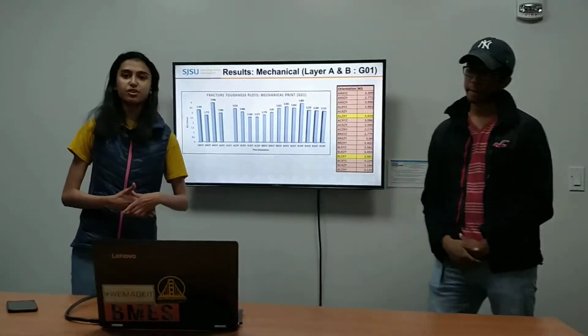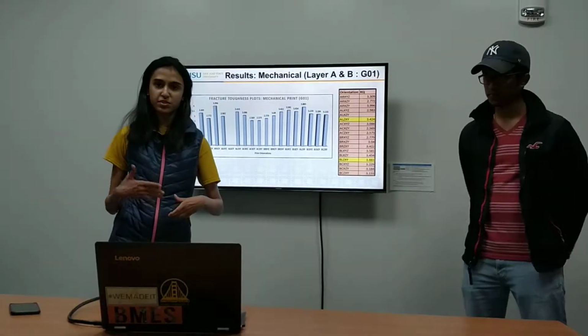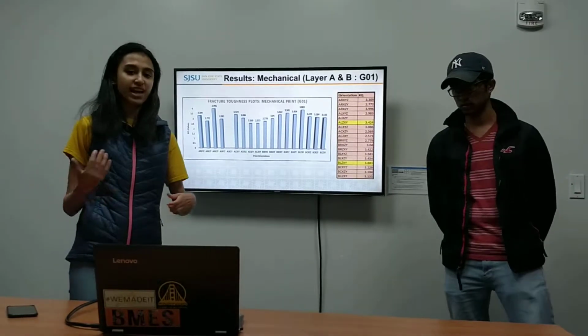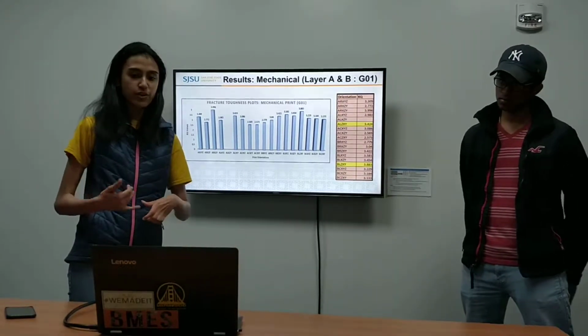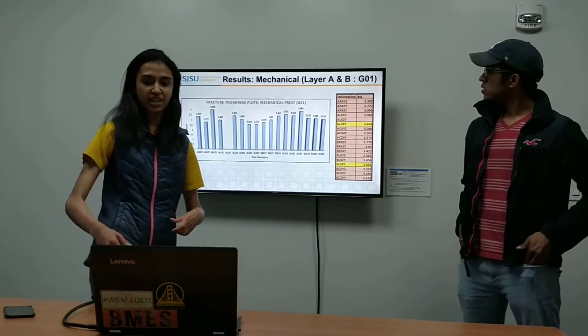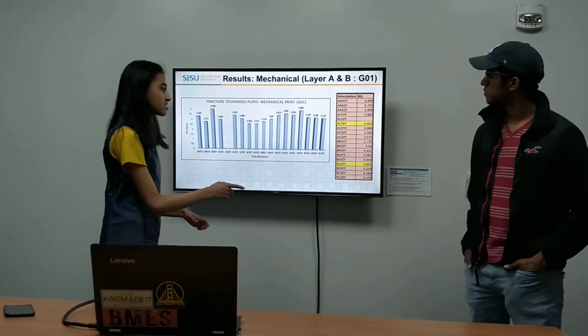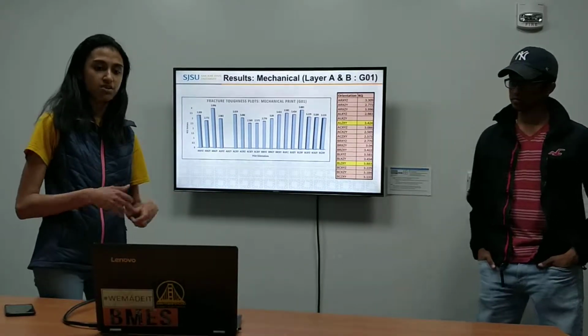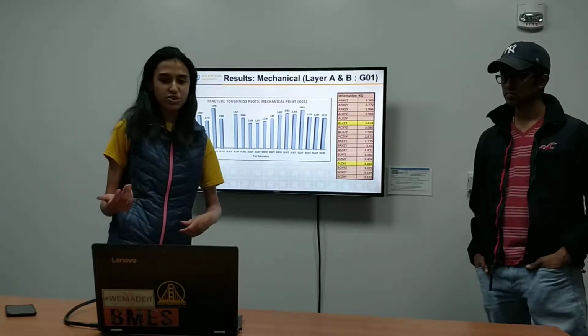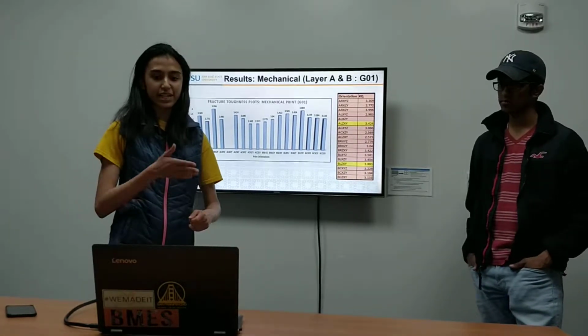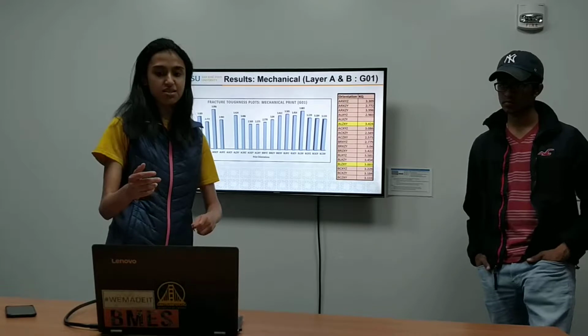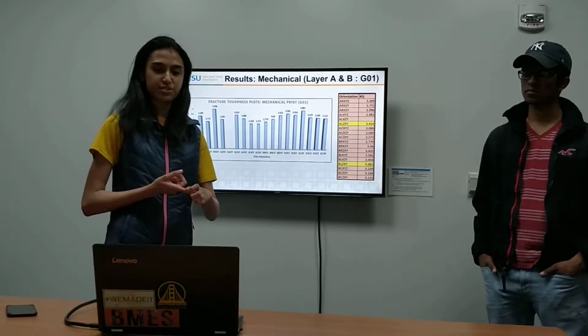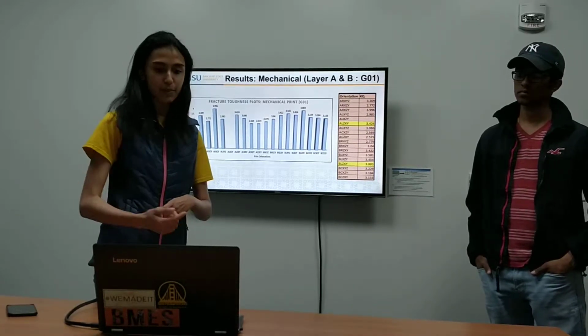So after all the 72 samples were fractured using Instron, and we gathered all the data using Blue Hill software, we generated various graphs and calculated all the KQ values as Shreet talked about in the last slide. So we generated bar charts for each orientation. So this is for printer G01, the first printer, and the mechanical print setting.